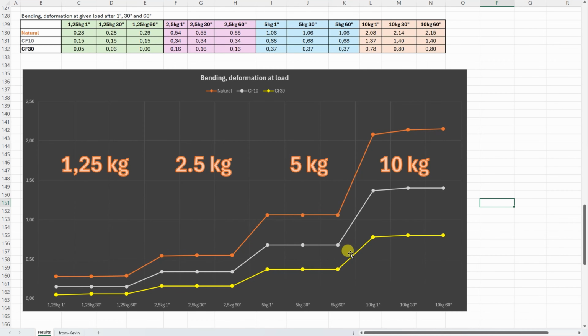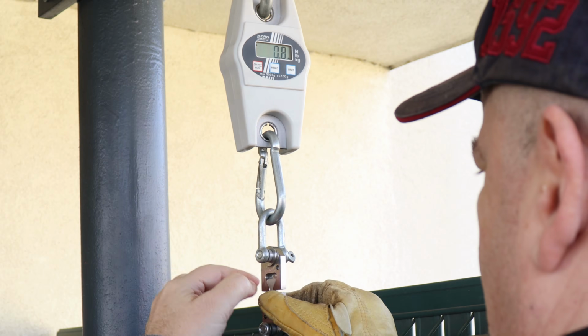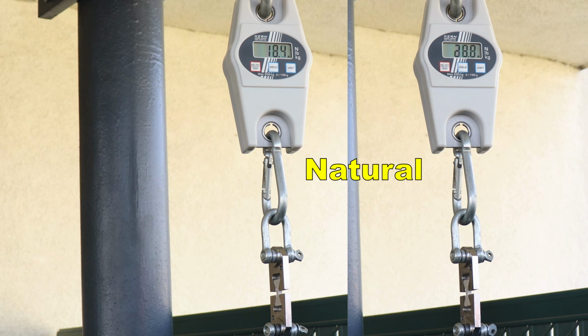Smaller numbers are better, so the best in this test was the CF30 and the worst the natural. With the natural PEEK we can see even some additional deformation under 10 kilograms during the time, so this starts to be too big a load for this material, but the other 2 carbon fiber versions are very stiff materials, especially this one, CF30. The tensile test with horizontally printed test objects, and I'm starting with the natural.